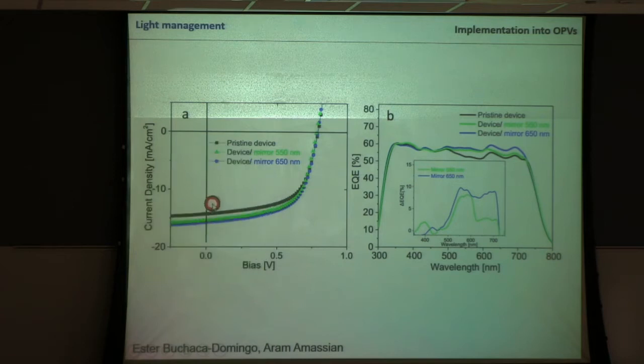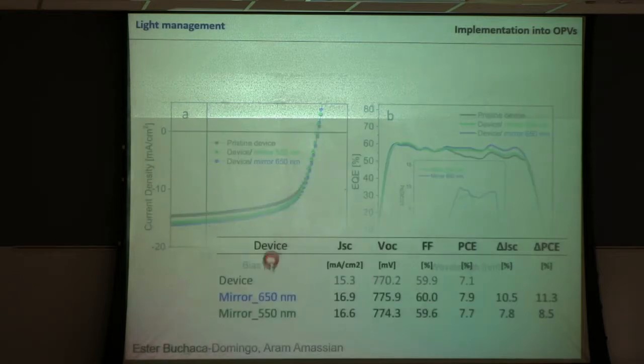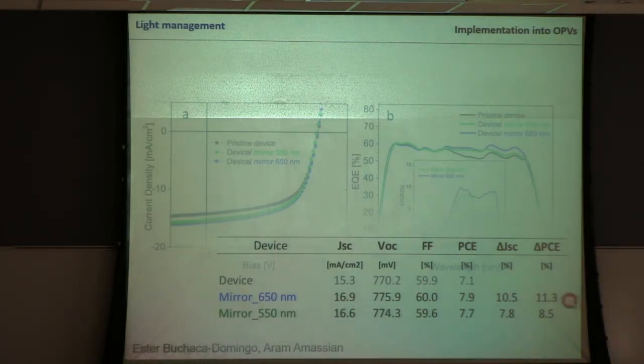This maybe doesn't look great, but we can measure it in the JSC. When we add the mirror, we do increase the JSC because we create more current, because we could absorb more light. And this is shown here. So when we have the usual device, and then devices that really reflect, especially in the regime where the material absorbs, we increase the short circuit current, and that leads actually to a significant increase in the efficiency.